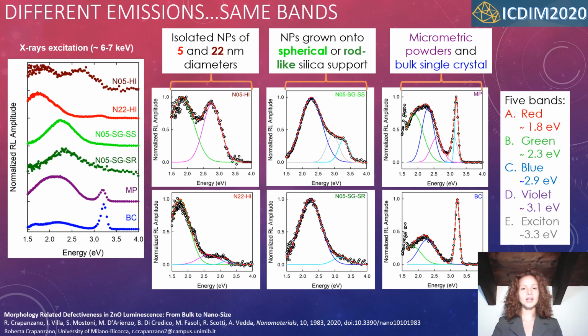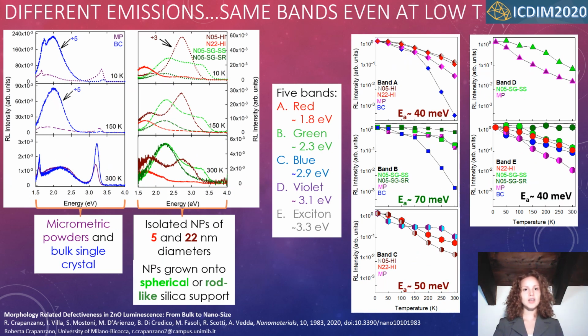The room temperature radioluminescence spectra of all the samples disclose different luminescence features. A Gaussian reconstruction of all the samples, anyway, disclosed the occurrence of a maximum of 5 emission bands throughout all the samples. These 5 bands comprise 4 visible defect-related spectral components and an UV excitonic peak. The same 5 emission bands were identified in the radioluminescence spectra recorded as a function of the temperature, even if their relative intensities change with the temperature.